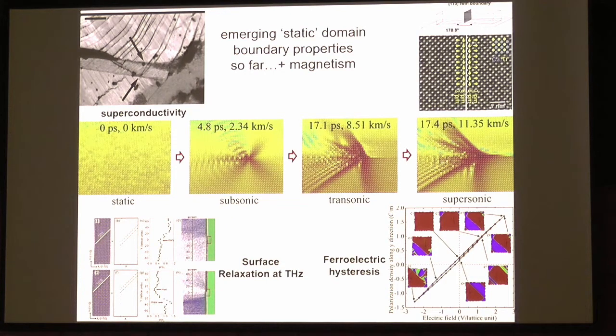And you have seeming ferroelectric hysteresis in a material which is absolutely not ferroelectric. And it comes from the fact that you have these domain walls in there which are moving forwards and backwards at a fairly high speed, and all of them have a polarity inside. So if you measure macroscopically, not discussing how you do that from first principles, but you just take these samples and measure macroscopically what the polarity is, then of course you have polarity in there, and you can see there's a narrow loop, and this loop comes from the movement of the dipoles which are attached to the wall, and the wall is moving. So that is the scenario of the kind of things I want to talk about.